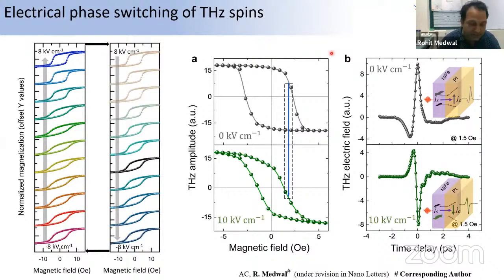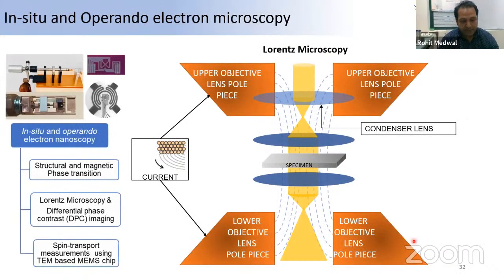So this is the first scheme where we have purely shown that voltage can be used to modulate the phase of the terahertz photon, and purely voltage can be used for modulating the terahertz photons in the spintronic emitters. And we are also trying to understand these effects in the TEM microscopy, which I just mentioned, especially the TEM with the Lorentz microscope and differential phase contrast imaging.